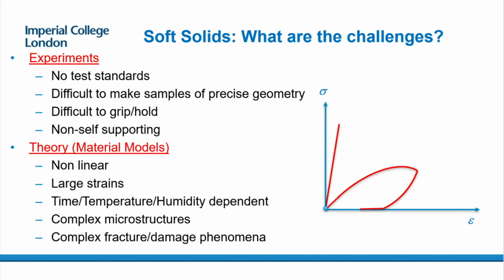So imagine here we have this stress strain curve and you test two materials. This is one material and this is another one here. This material, its stress strain relationship is linear. It only goes up to small strains. This material is very nonlinear, and this could be happening right from the beginning. There's no initial linear slope. And it also goes to large strains.